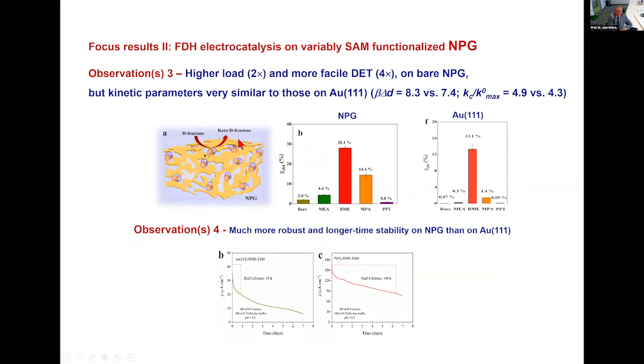If you go to the nanoporous material, then we find there's a higher load and a more facile direct electron transfer. And these two do not necessarily match, because if you go to this different environment in the nanoporous material, the orientation of the molecules can be different. And what we see is, in fact, the kinetic parameters are not all that different. For nanoporous gold, 8.3 versus 7.4 for the single crystal, and the same with the actual rate constant.